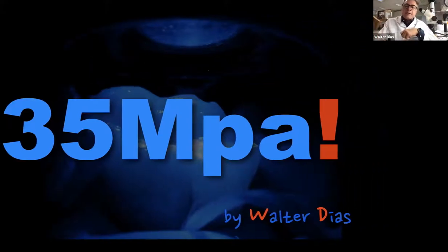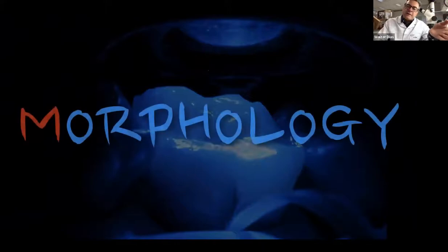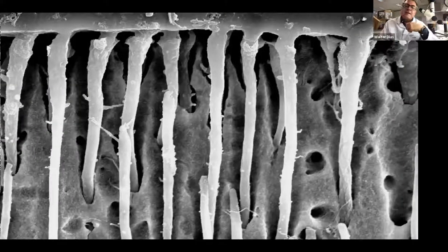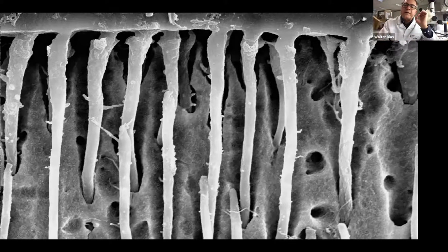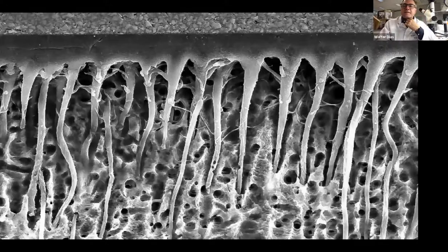Very well. So how do we achieve this in our practice? First, you should always be applying your adhesive to fresh dentin. What you see here are saturated resin tags with a cross section. This is my work that I did during my thesis. I removed the dentin from the side also so you can look at the resin tags. It's a cross section that I etched from the side, and you can see a seamless penetration of these resin tags by the adhesive.